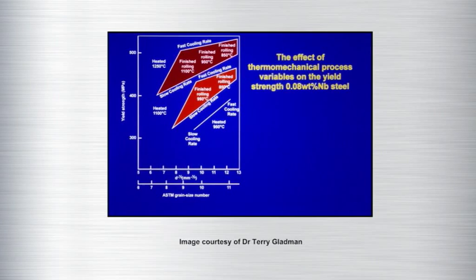We were able to produce charts which showed what was attainable with precipitation strengthening and grain refinement. This was quite significantly in excess of that for normal mild steel. In fact, the addition of 0.04% of niobium could result in a doubling or even a tripling of the strength. This was very important commercially because none of the other factors could produce those increases in strength at an economic cost.